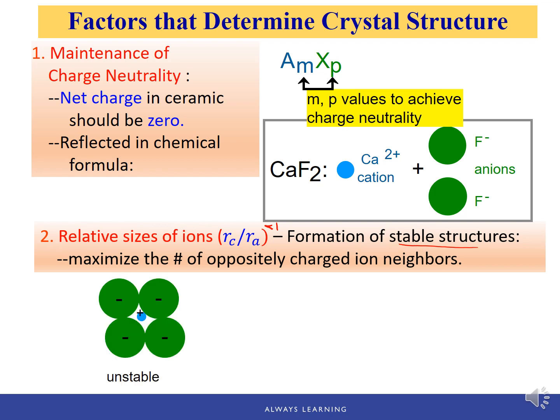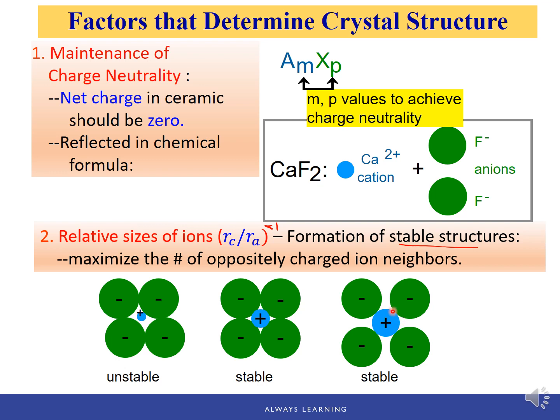For example, this is an unstable crystal structure, because we have anions forming a close-packed structure and there is an interstitial site, looks like a diamond site, right? Or a void between those anions. We can place one cation in this void, or interstitial site. But since this cation is too small, it's not in touch with the nearest neighbors, those anions. So this is an unstable crystal structure. And this one is a stable structure, because this cation fits perfectly into this void and is in touch with all the neighboring anions. And this can also be a stable structure.